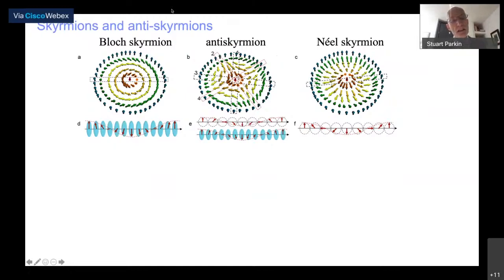And in a Bloch skyrmion, I hope you can see in this cartoon, the magnetization rotates from an up direction to a down direction by rotating parallel to the boundary. Whereas on the right-hand side, you can see a Néel skyrmion. This Néel skyrmion, the magnetization rotates from an up direction outside this small object to a down direction inside by rotating along the radius of this object. So they're two very different objects. Now it turns out the chiral domain walls that I just discussed for a racetrack have a Néel domain wall structure. But it turns out then the skyrmion was discovered about 10 years ago in a B20 compound, manganese silicon, and these show these Bloch skyrmions on the left.